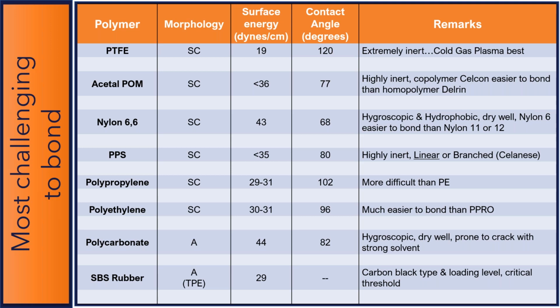When it comes to nylon 6, nylon 66, look at the morphology on all of these: semi-crystalline, semi-crystalline, semi-crystalline. So when it comes to nylon 66, it happens to be both hygroscopic and hydrophobic. So for any of you that are experts in this field and you want to say Sabrine is full of it, he doesn't know what he's talking about, because how can a material be both hygroscopic and hydrophobic? Well, one is a bulk material property, meaning that it absorbs moisture. The hydrophobic portion is a surface attribute.